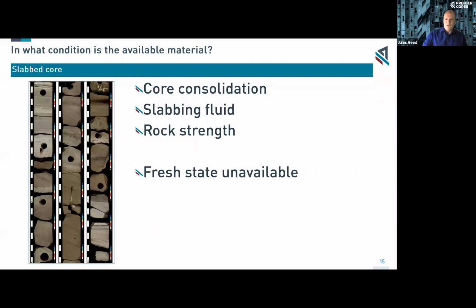Slab core, what do we need to do with slab core? Well, we have to consider core consolidation. We have to consider what slabbing fluid was used, because it could have been done in water, or a saline water, in oil, or with air. And if you go back 20 years, slab core was probably done with tap water. And if you've got lots of water sensitive minerals present, that's not going to be good. There's also, over time, the fluids in this slab core will be evaporating. That could lead to salt precipitation. Depending on where it precipitates, salt precipitation could lead to weakening of the structure. And so you may end up with this slab core degrading in quality over time and over the number of years that it's stored.